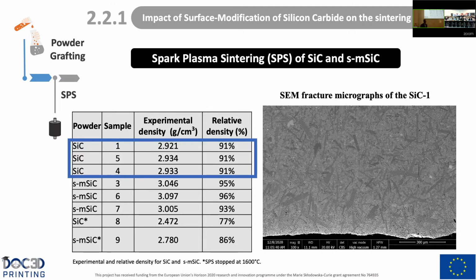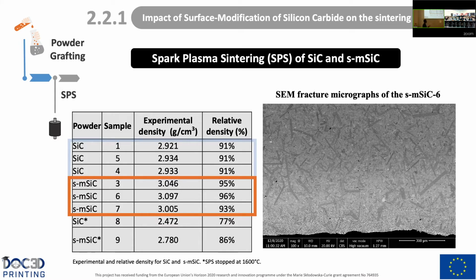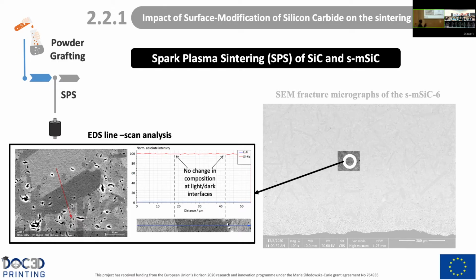Here, regarding the microstructure of the material, we can observe some porosity that is increasing at the edges of the material, and we can observe some brighter and darker areas. If we compare with the microstructure of the surface modified silicon carbide, again we observe porosity increasing at the edges of the part, and again these brighter and darker areas, so we observe similarities between both microstructures. But if we zoom in on this part and perform EDS scan analysis to know what these brighter and darker areas are on the surface, we cannot observe any change in the composition.